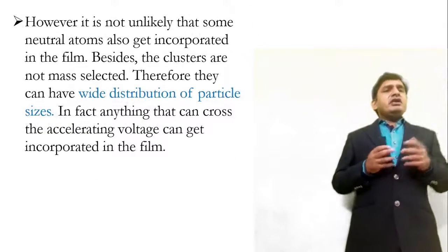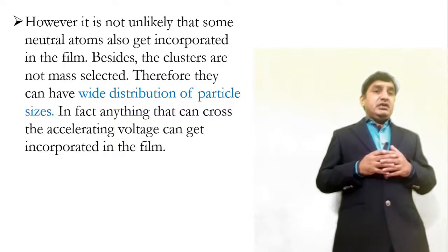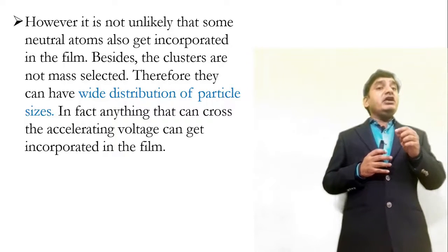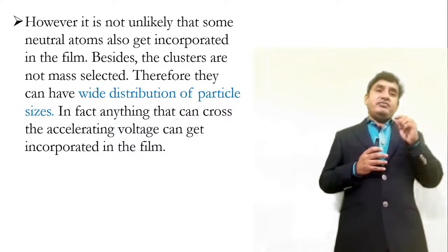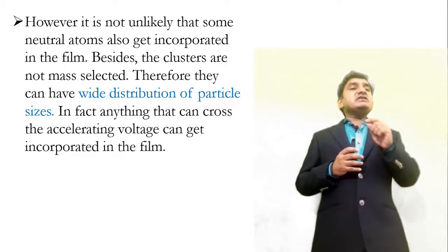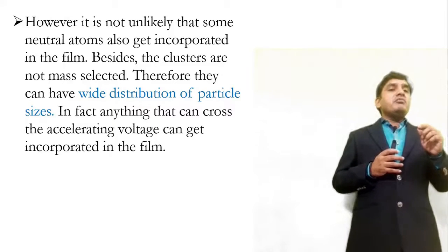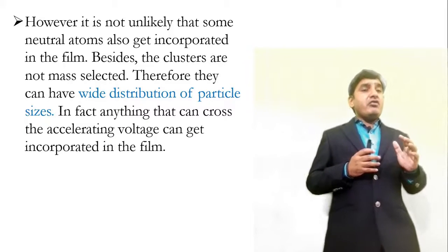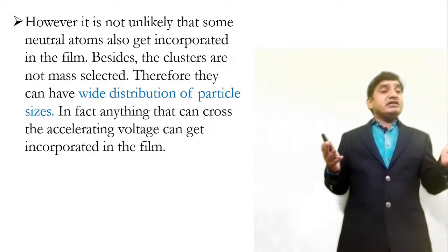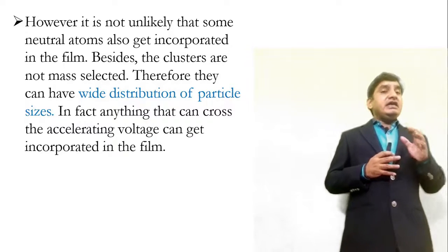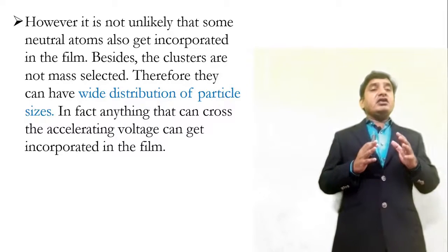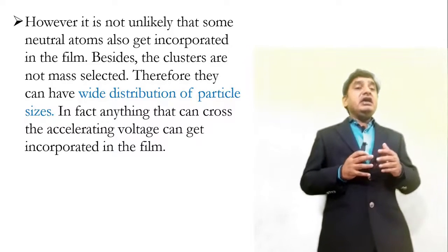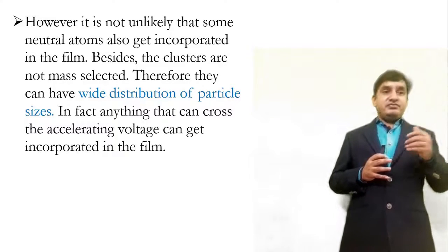However, it is not unlikely that some neutral atoms also get incorporated in the film. Besides, the clusters are not mass selected. Therefore, they can have a wide distribution of particle size. In fact, anything that can cross the accelerating voltage can get incorporated in the film.